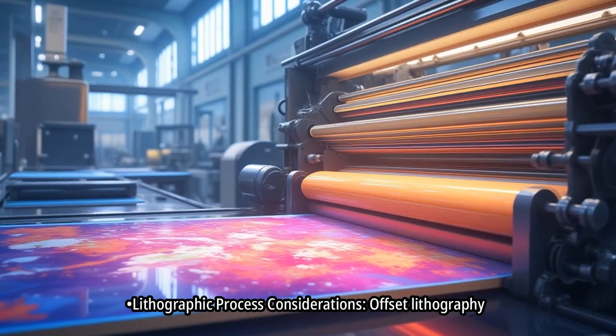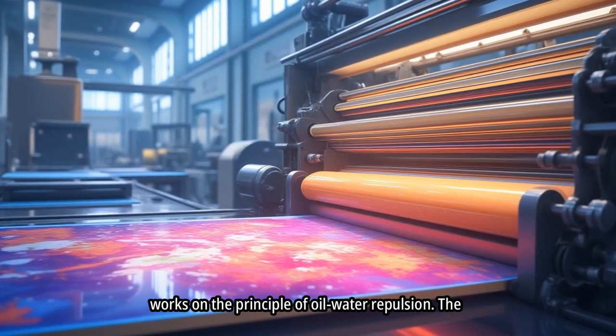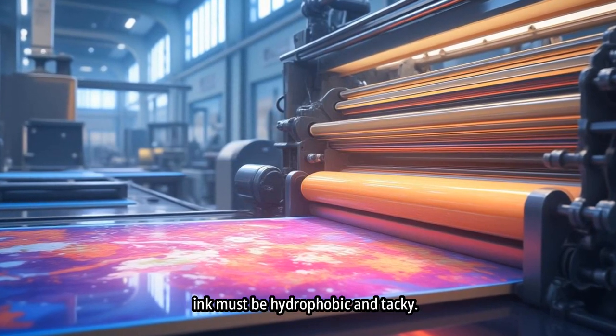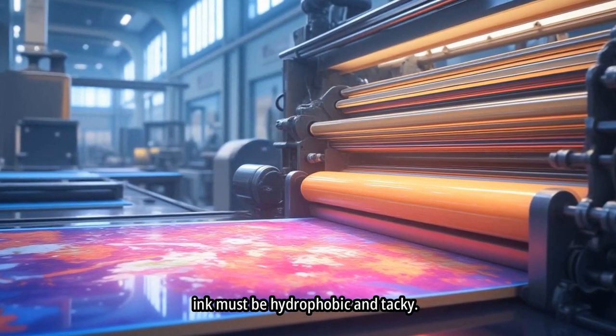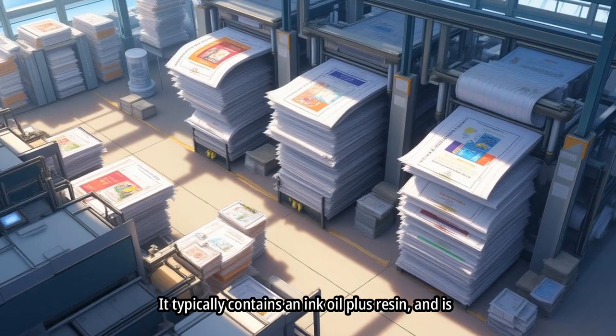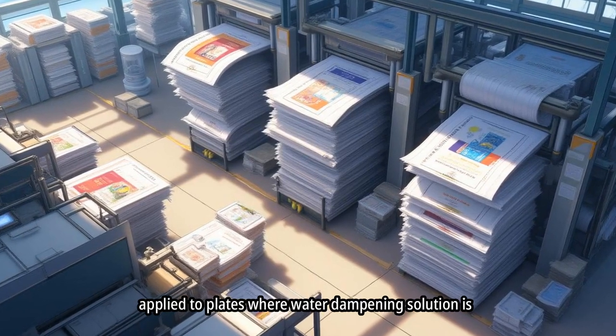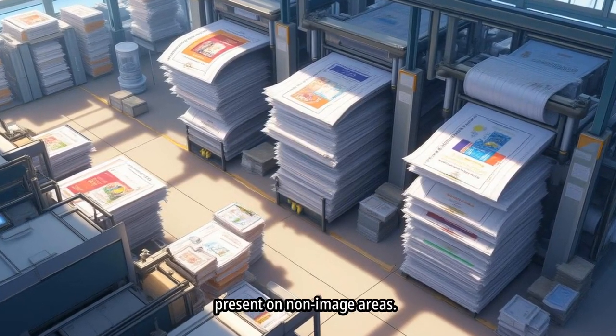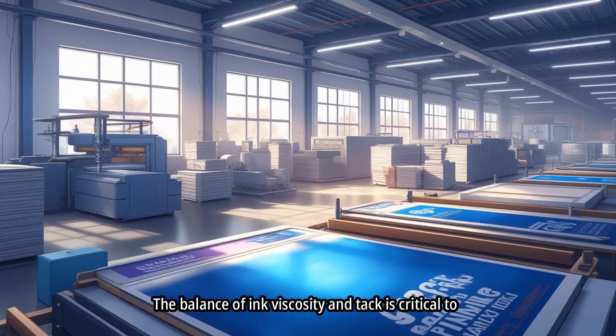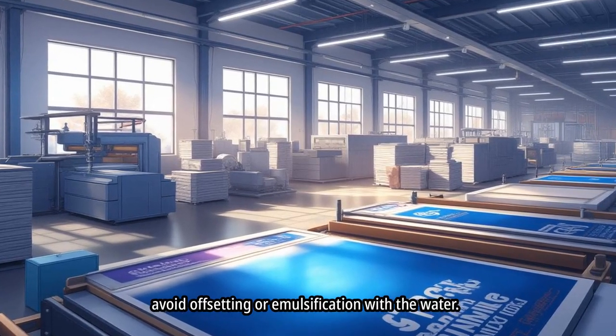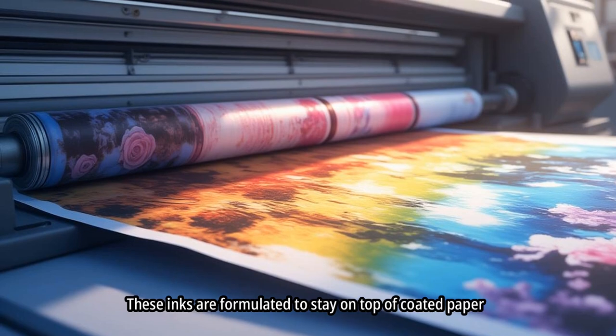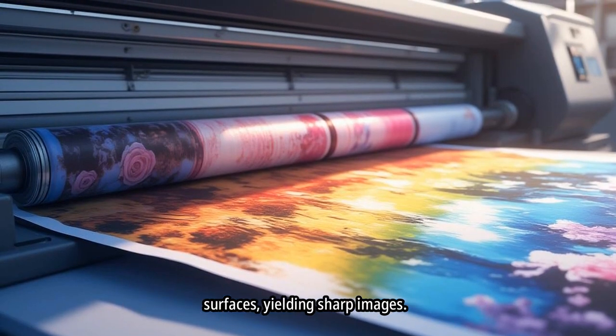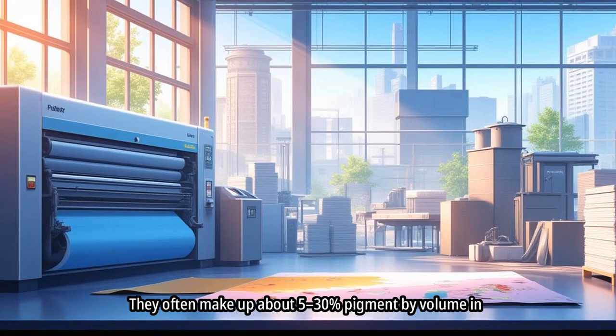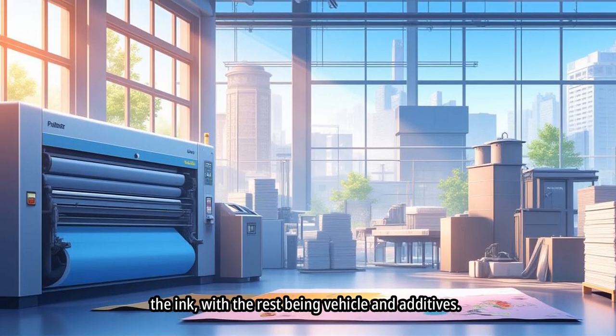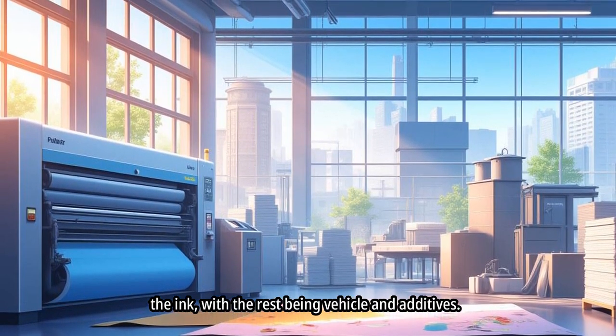Lithographic process considerations. Offset lithography works on the principle of oil-water repulsion. The ink must be hydrophobic and tacky. It typically contains an ink oil plus resin and is applied to plates where water-dampening solution is present on non-image areas. The balance of ink viscosity and tack is critical to avoid offsetting or emulsification with the water. These inks are formulated to stay on top of coated paper surfaces, yielding sharp images. They often make up about 5–30% pigment by volume in the ink, with the rest being vehicle and additives.